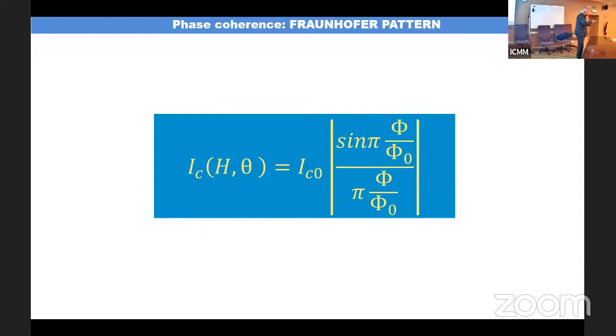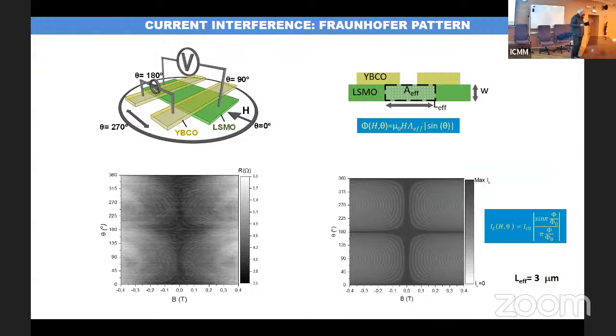In the end, this Fraunhofer pattern is a flux matching effect, and changing the angle is a way of closely probing the flux matching. So the idea is that when you rotate the magnetic field in the plane, the magnetic field necessary to amount a flux quantum is angle dependent. So you end up having two periodicities, one angular periodicity and one magnetic field periodicity. Remember that the critical current goes to zero for every flux quantum. And this is a simulation of what we expect according to the Fraunhofer expression. And this is what we measured, that we reproduced consistently the angle periodicity and the magnetic field periodicity.